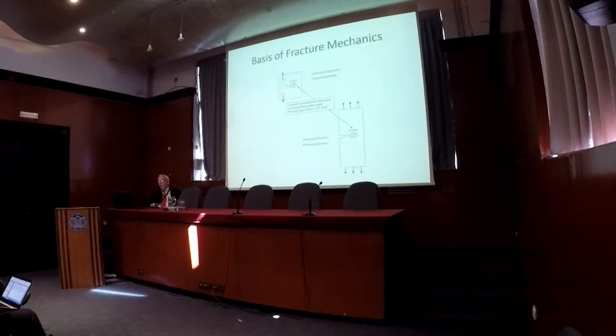So that's that. Now, the fracture mechanics approach is this: since the distribution is unique for mode one, no matter what the geometry, you can use that for transferability. That is to say, if you take a geometry that's more like a specimen you would use in the laboratory, and this is one, but probably doesn't represent any structure, and test that specimen in the laboratory, and in terms of K find out what is happening, then you can transfer that to something more like a structural element. So in my little schematic here, this represents the laboratory test, this represents the geometry of some structural element, and you can transfer the behavior in terms of K.